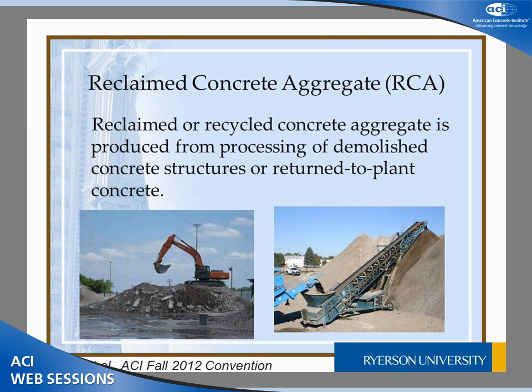So, what is reclaimed or recycled concrete aggregate? It's basically the concrete or aggregate that's recycled from either demolished concrete or returned-to-plant concrete. The difference is that demolished concrete comes from a structure that has reached the end of its service life and is then demolished — all the concrete can be recycled and used as aggregate in new concrete. The return-to-plant concrete, on the other hand, is rejected concrete, perhaps with a service life of less than one day, dumped in the backyard of a batch plant and then processed as recycled concrete aggregate.